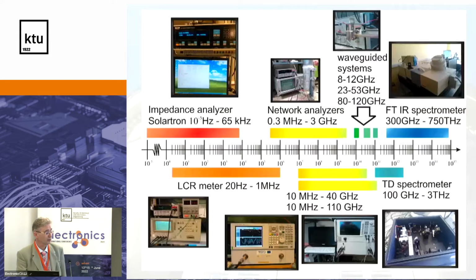And finally, the most important part of my talk. When you have a material and you want to use it for cars or for mobile telephones or whatever, or for superionic batteries, you need to characterize it in a broad frequency range. So what we have is we are starting from an impedance analyzer, which goes from 10 to the minus 5 hertz. So extremely low frequencies, extremely long wavelength. And as a physicist, I would say that no experimentalist has the patience to wait so long for the results, because it will take about one week to get a reasonable result. So usually we are measuring from 10 to the minus 3 hertz, and this equipment goes up to 65 kilohertz, and the new one goes up to 1 megahertz.